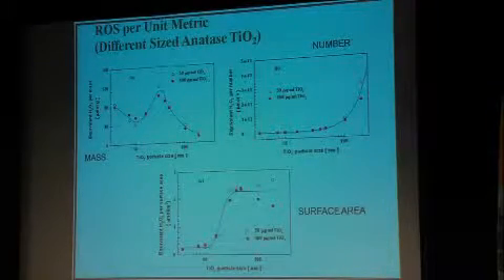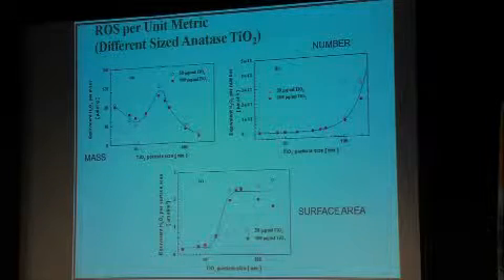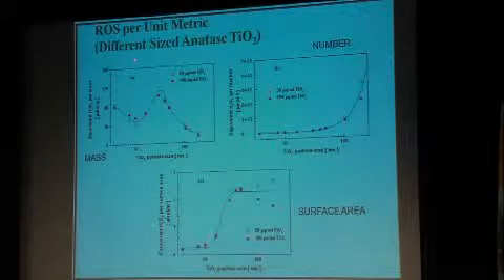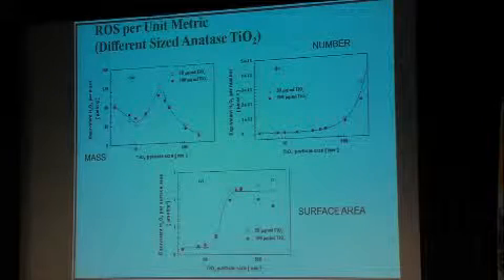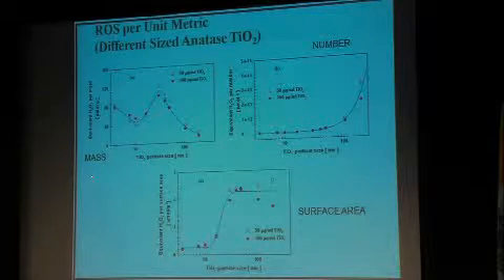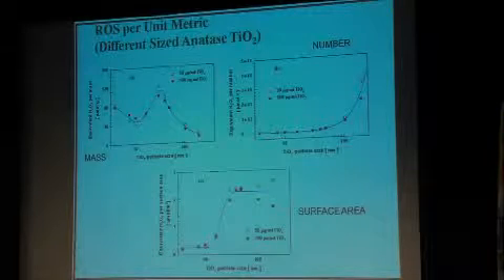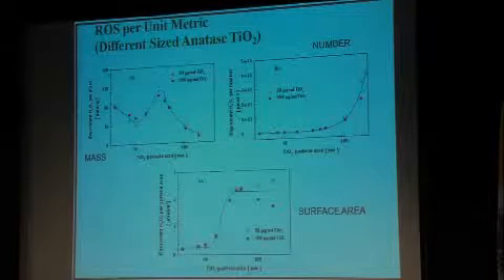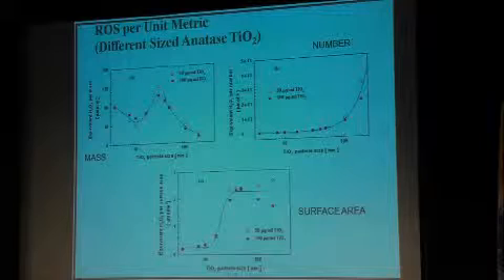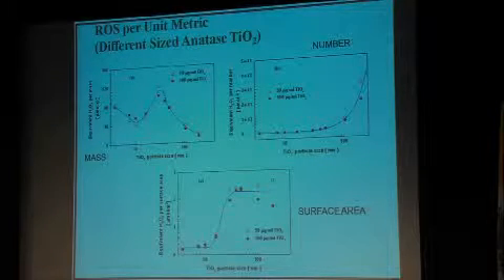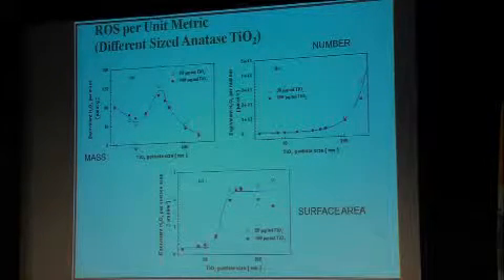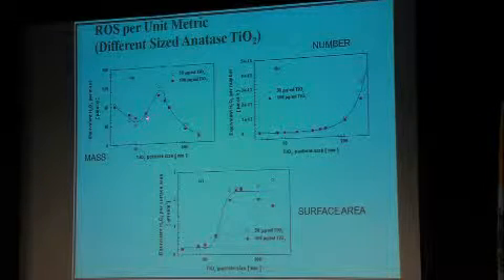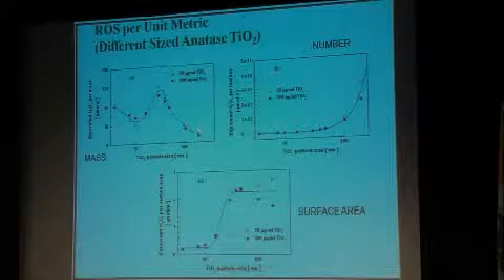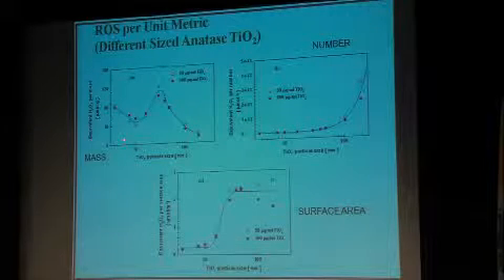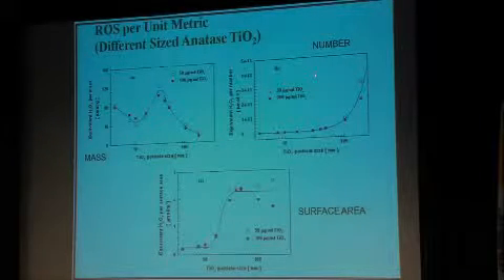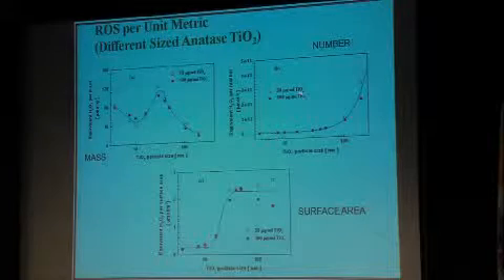These are some ROS measurements that were done in Gunter's lab. So different size anatase, and here comes the metric. Now toxicologists typically use a certain mass concentration of the material. If I take the same mass concentration of 4 nanometers and 200 nanometers, obviously the surface area is way greater for the 4 nanometer material. So instead of doing it by mass, and you can also see there's no particular trend that comes out. Now if I do it with number, there seems to be some kind of trend, but very difficult to interpret.